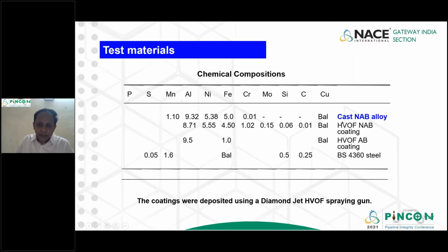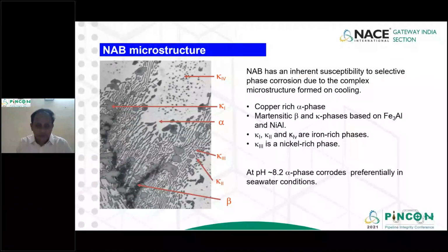Then I'm comparing with the NAB coating, which is done using a spraying gun, the diamond jet HVOF spraying gun, and coated on a bare steel surface, which is BS 4360 steel. This is only aluminum bronze, where you have a variation in the composition of aluminum, nickel, and iron, in addition to some other components like molybdenum and silicon. But the wonderful thing about this alloy is its microstructure, which has five different phases: alpha, beta, kappa. Because of these different phases, it has a chance of going into selective phase corrosion.